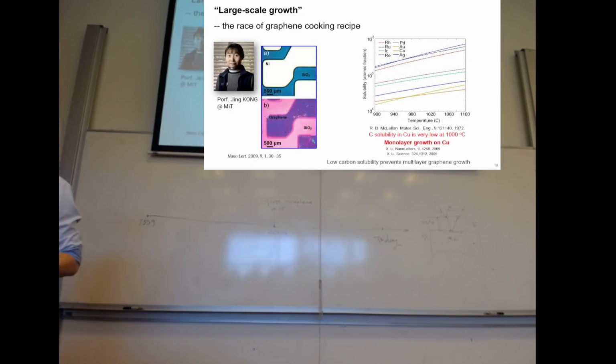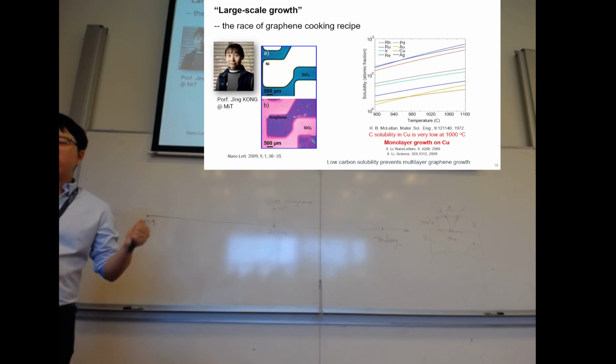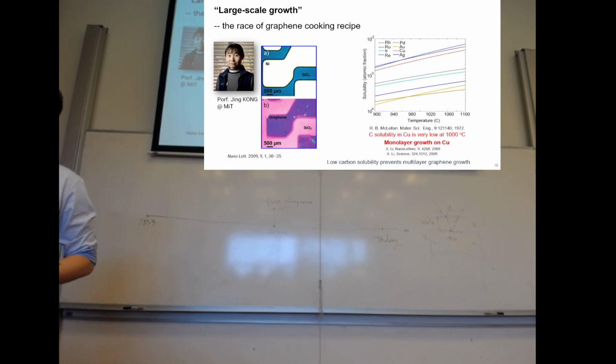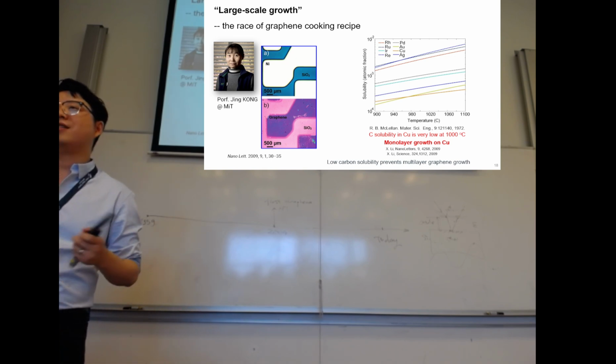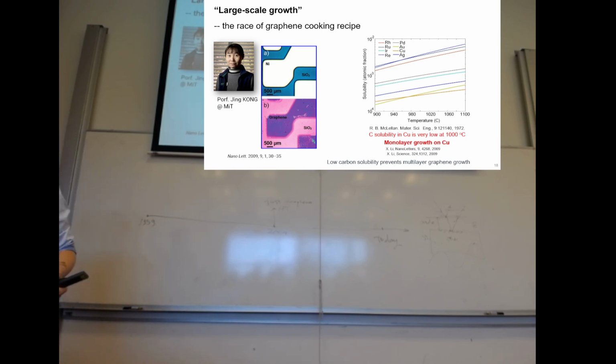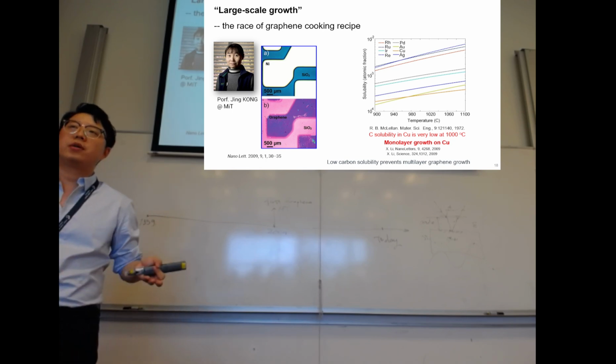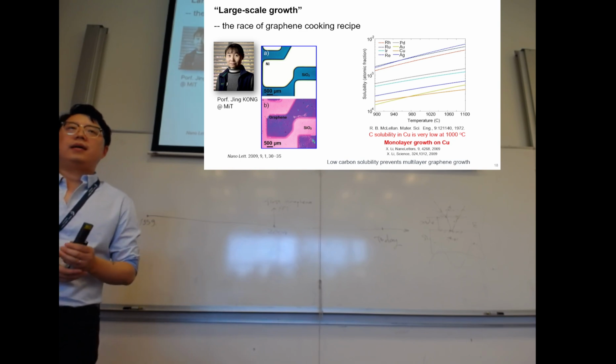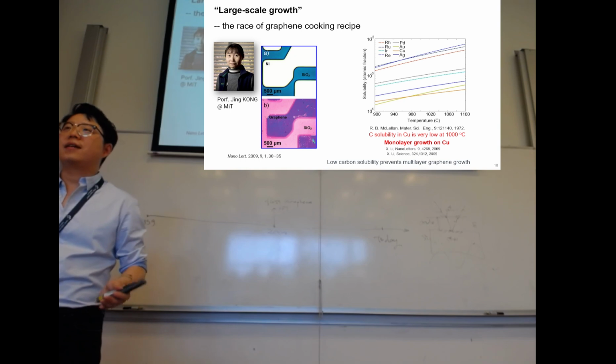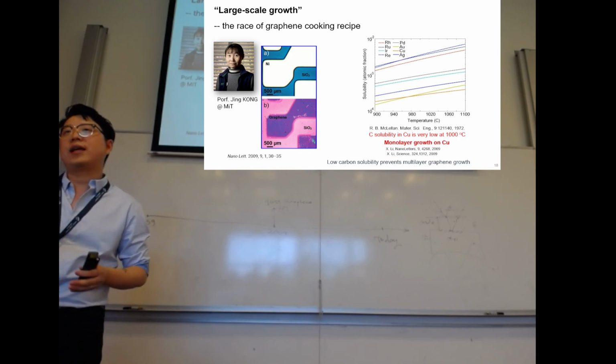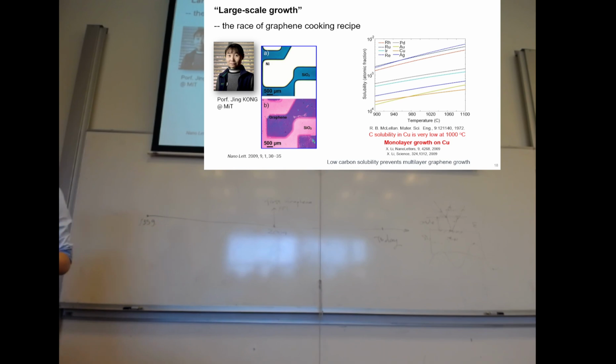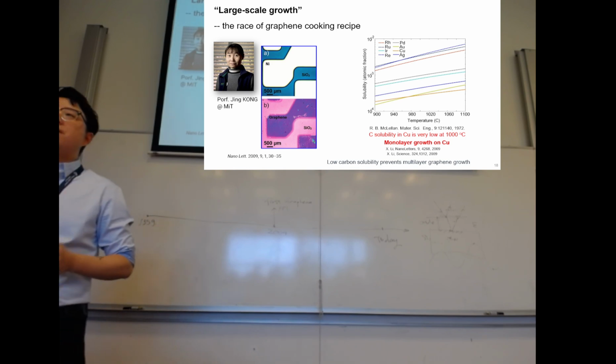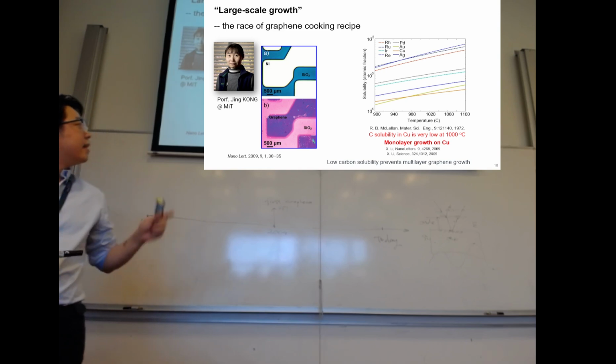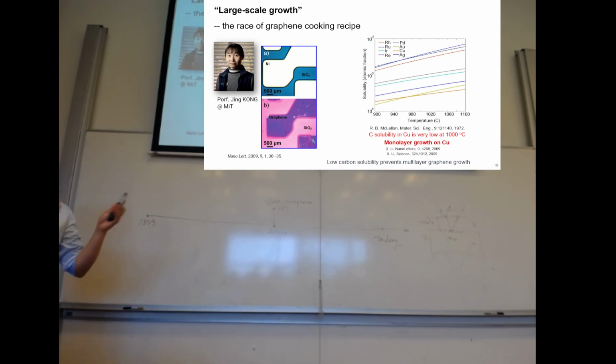So nowadays it looks very easy, but growing graphene on top of a metallic surface is not really that useful, because we need electronic devices which are not shunted, right? If you grow graphene on top of copper or iridium, all these substrates are more conducting than graphene. You don't detect anything except the morphology of graphene. That's not very useful. So people found that maybe you can get rid of this substrate, and that's the first experiment. One of the very first experiments from MIT, Professor Kong's group.